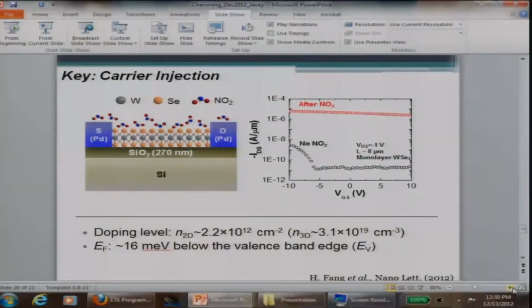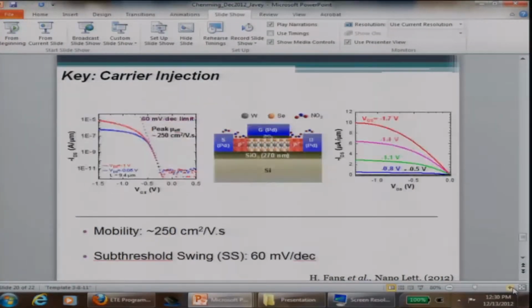So if you do this doping, you go from a device that looks like this, that has strong gate dependence, the currents are low, to a device that has weak gate dependence, but the currents are very high. It's now heavily doped. You can extract the doping concentration. The doping concentrations are high enough, they're degenerately doped for this particular semiconductor. And it's good enough for making now heavily doped contacts. So that's what we did.